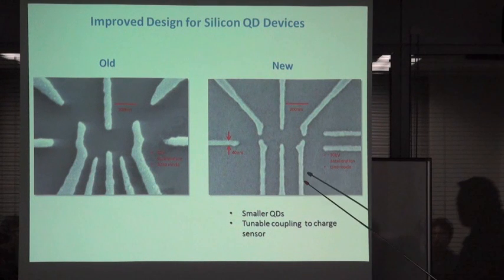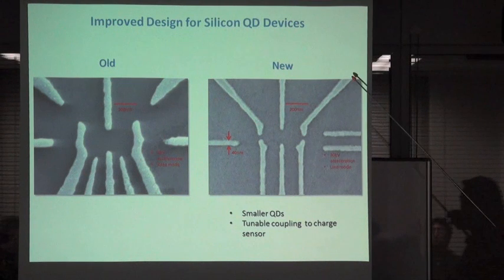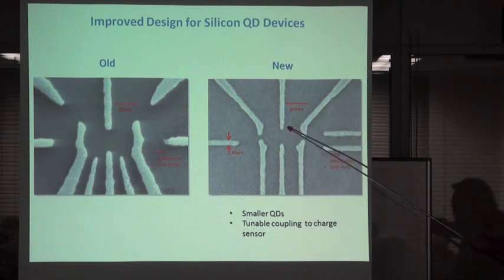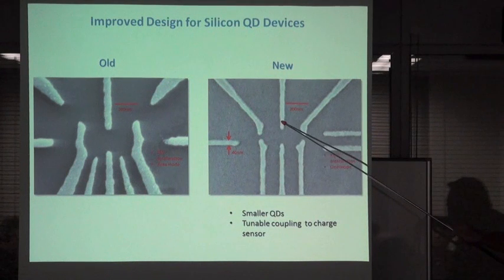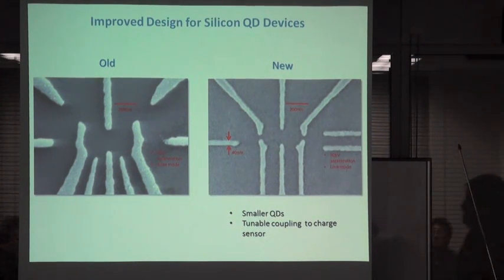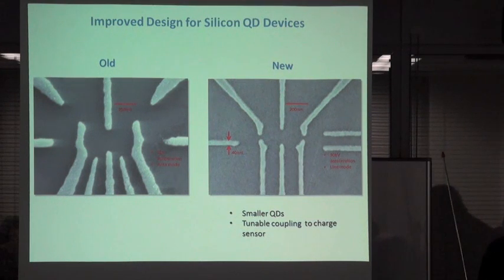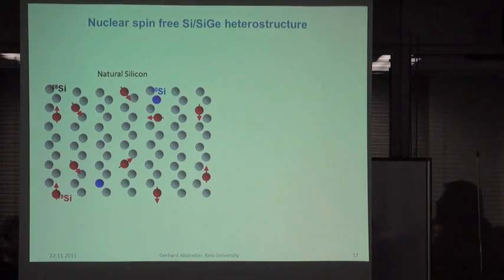So more recently, we have made new devices with different e-beam, let's say, parameters, which have much narrower lines, and altogether the size is shrunk, and they can control the tunneling barrier better here. And with this, we can now really go to the single electron limit in the case of silicon. And the other thing we can do is go to a nuclear spin-free system.